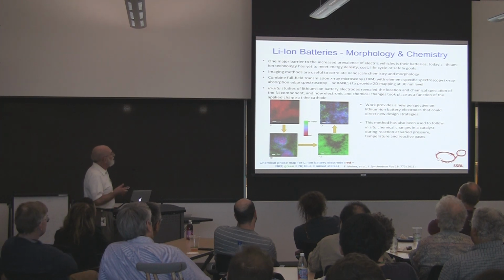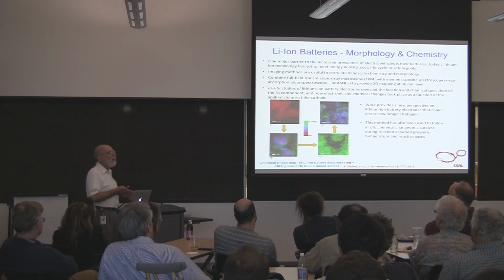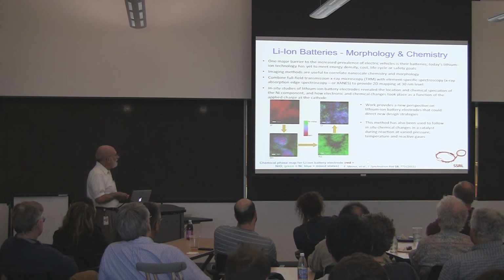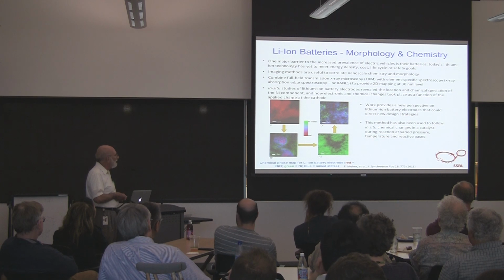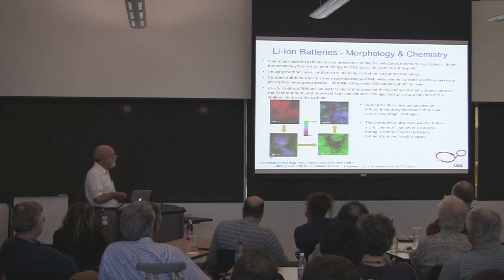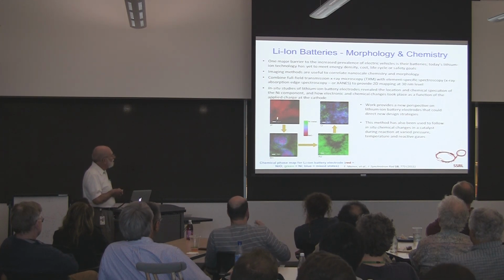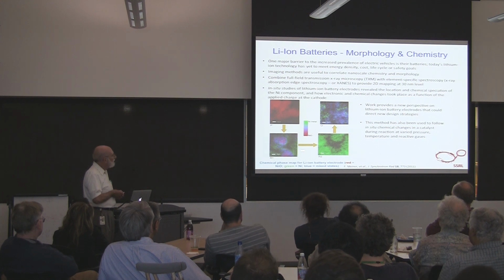And in their case, the cathode of the battery was made of nickel, which in the charging-discharging cycle cycles between metallic nickel and nickel oxide, where what you see in red is nickel oxide, what you see in green is metallic nickel, and blue is shown in mixed states. So as you go through the charge-discharge cycle, you can see that you go from the nickel oxide to the